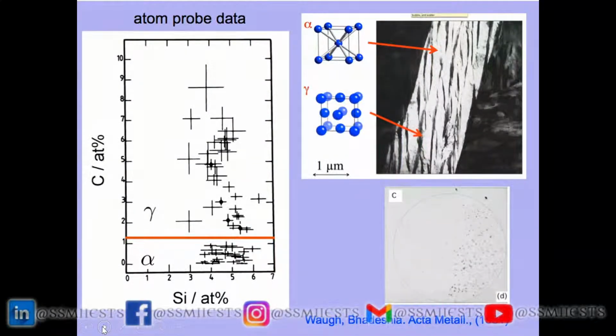These are experiments I did back in 1981 with Bob Waugh, where we used the atom probe, and the image at the bottom right-hand side shows the carbon atoms segregated into the austenite, and the ferrite has lost much of its carbon. But if you do a lot of experiments, you find that actually the concentration of carbon in the ferrite is very high. And we assumed back in 1981 that this was because it was trapped at dislocations. And since 1981, the instruments have become more sophisticated. So if we go to the next slide.